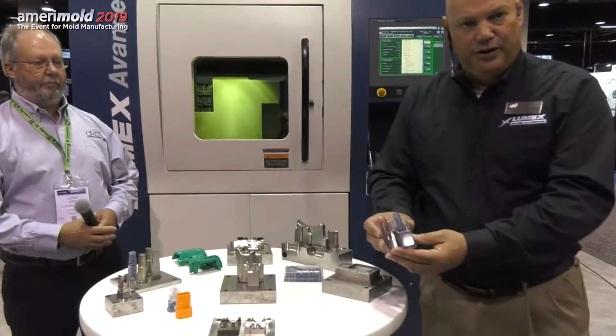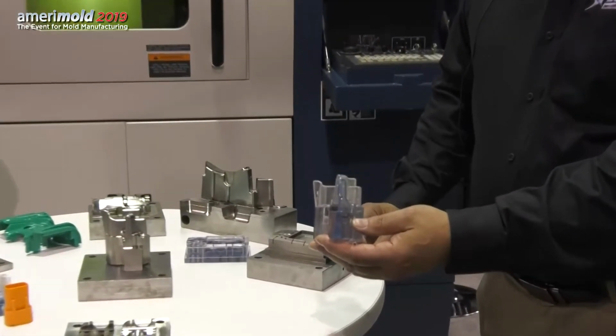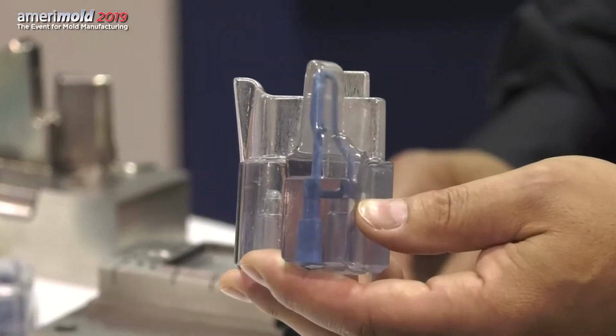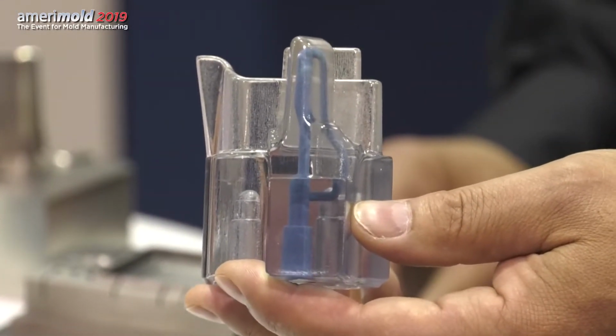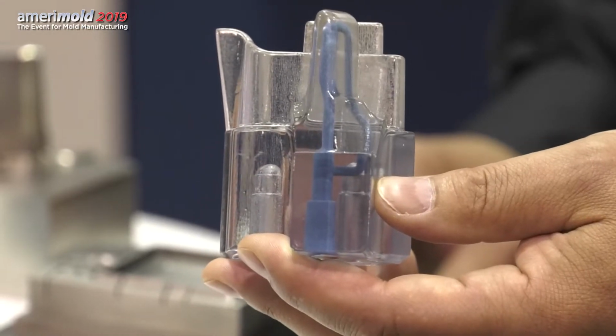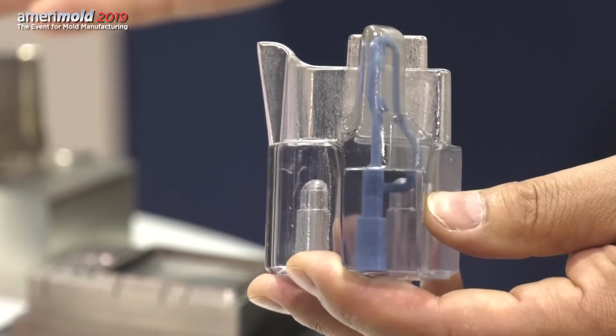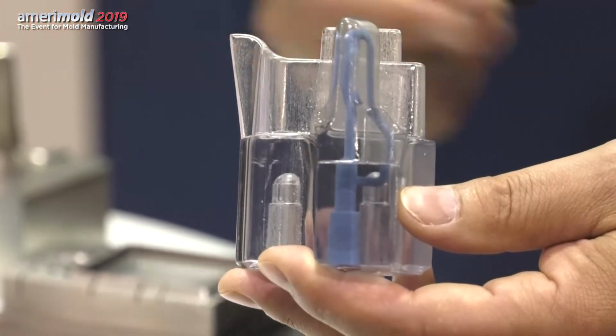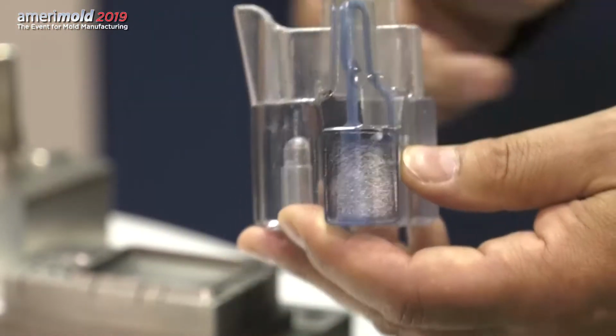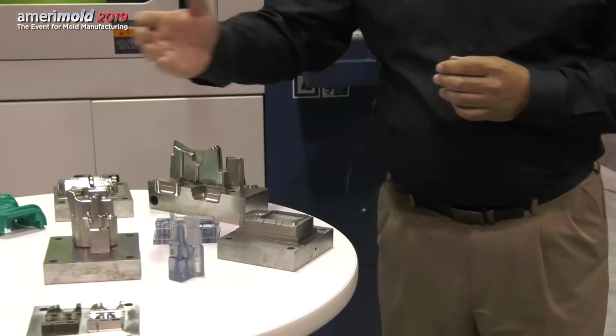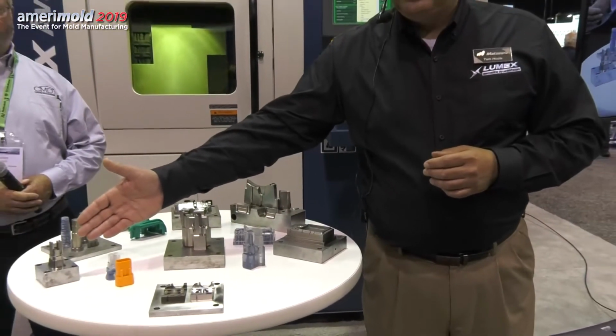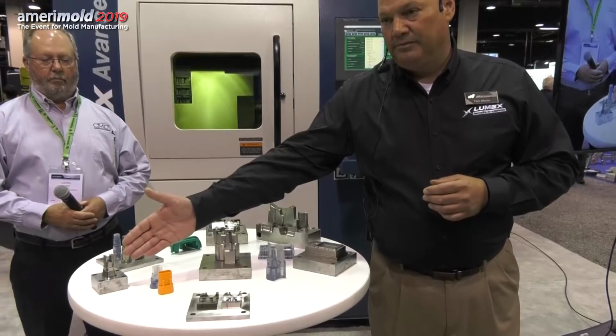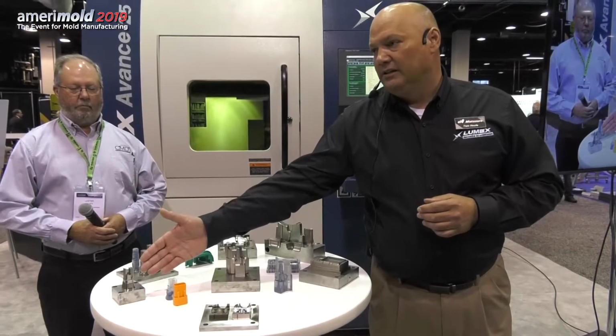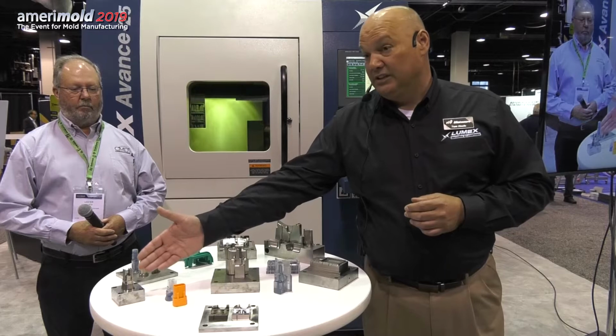As you'll see some of these parts on the table, here's a plastic version of the conformal cooling in a die-cast insert. This allows the customer to heat and cool the mold rapidly to prevent the problems with heat shock. They used to use about 20 of these inserts every year, and now they use 2 per year. So the life cycle of the part has increased significantly. Again, because we're machining as we grow the part, we can get very fine detail without EDM. In a lot of cases, we can virtually eliminate the use of EDM for deep ribs and deep pockets.